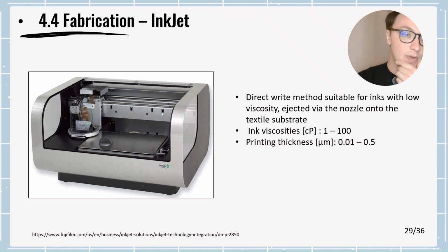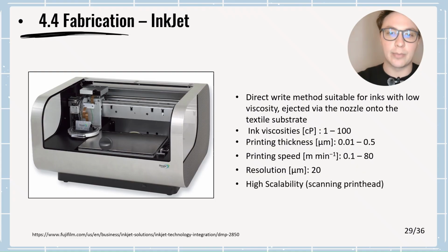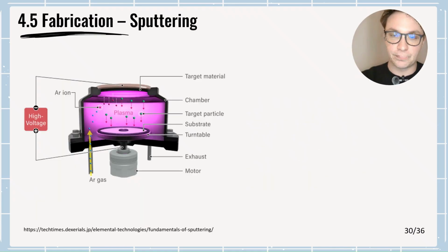The thickness is quite interesting because it can go down to 0.01 micrometer. It's not very fast, I would say. The resolution can go down to 20 micrometers, so very thin and very accurate, I would say, in the design process, and it's quite scalable. So again, with a scanning printhead, we can achieve high scalability.